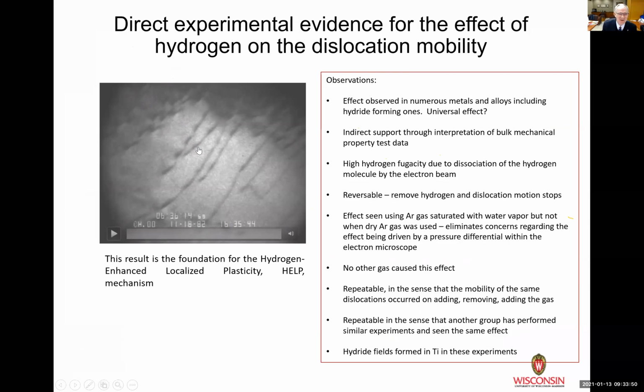Professor Kubota was very kind when he talked about my 1984 work and the fact that it led to some recognition from the Department of Energy. So this is, in fact, one of those early movies that we made about adding hydrogen into an electron microscope, applying some load, and seeing what would happen to the dislocations. In this particular example, we applied some load. We knew these dislocations were mobile. We took the load off the specimen and then simply added hydrogen gas into the electron microscope.